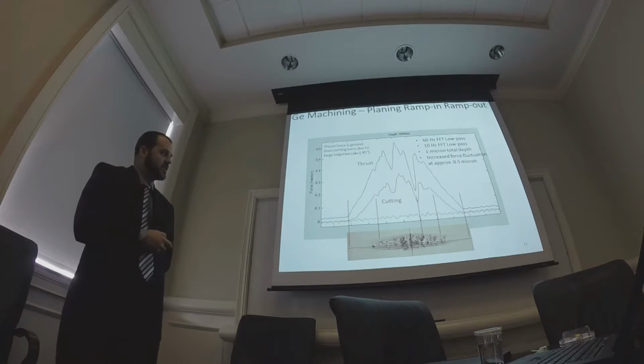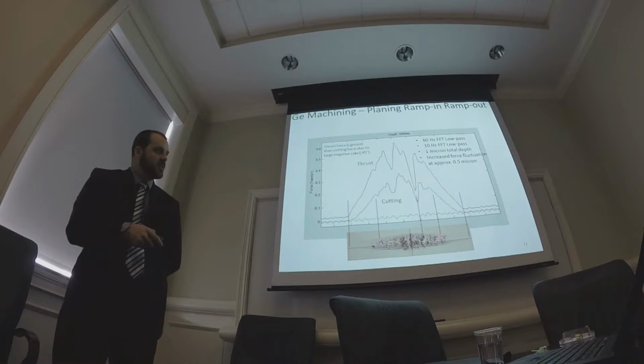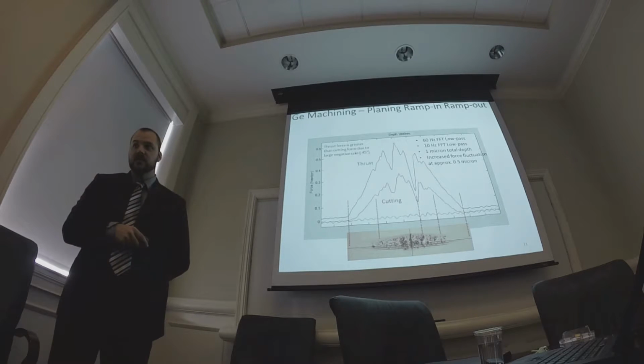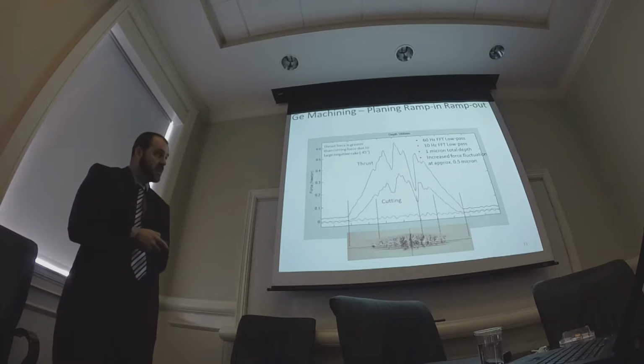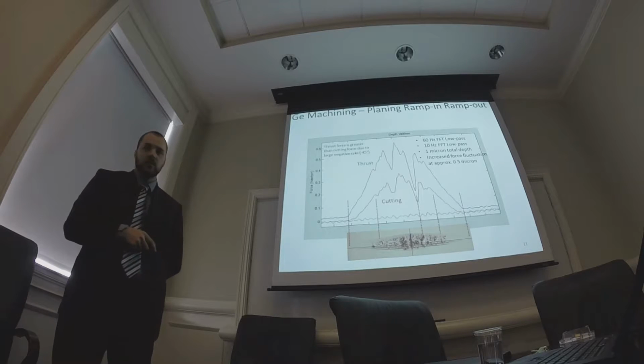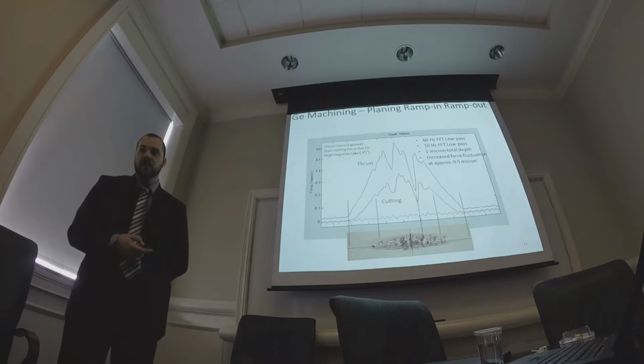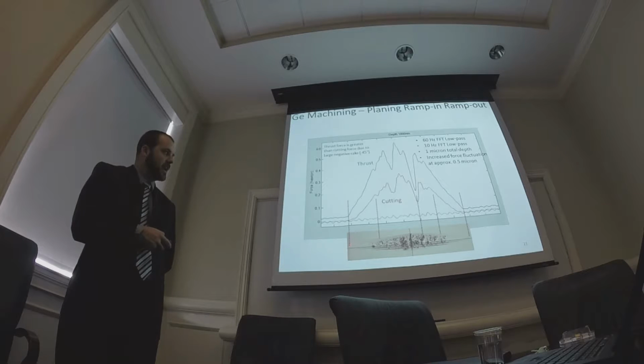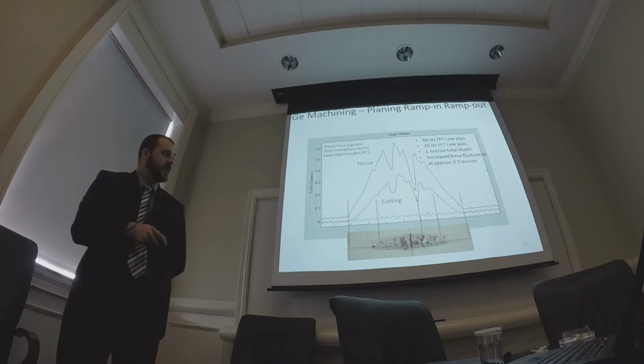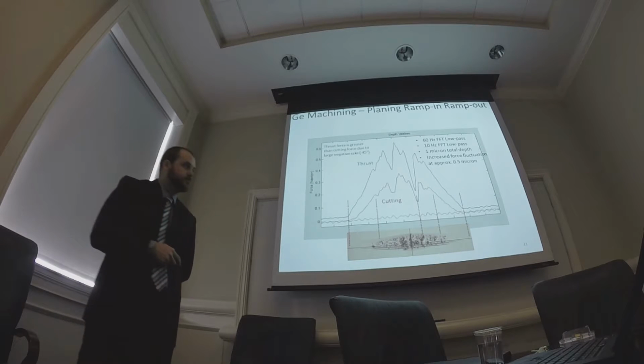Evans pointed out when I presented this originally, should this have been symmetric, or would we have expected this to propagate more into the surface? We were talking about that, and we believe that the surface prior was non-fractured. So if we recut on top of this, I would expect the brittle fracture to go a little bit further this direction than the other side.